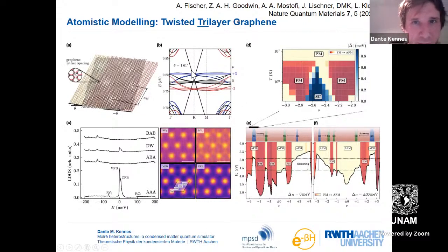So B shows, in black, just the non-interacting band structure. And you see that they have these flat bands here at the center. They also have a dispersive Dirac cone. That's because on top of these flat bands, they look at twisted trilayer graphene, not twisted bilayer graphene. But they also have all these bands here and many, many more, which are not shown. And these are all the tens of thousands of bands that are in the unit cell. And then they can look at instabilities.